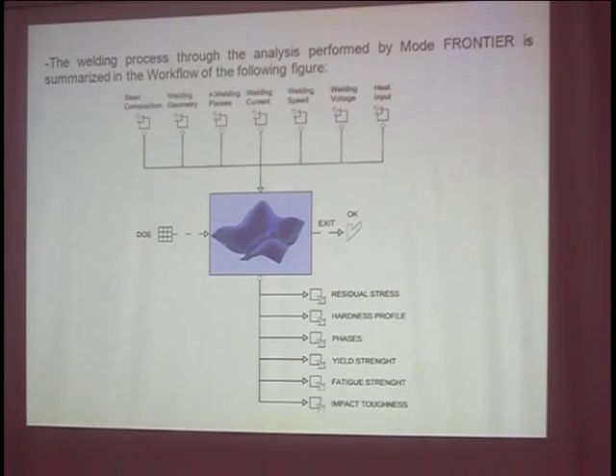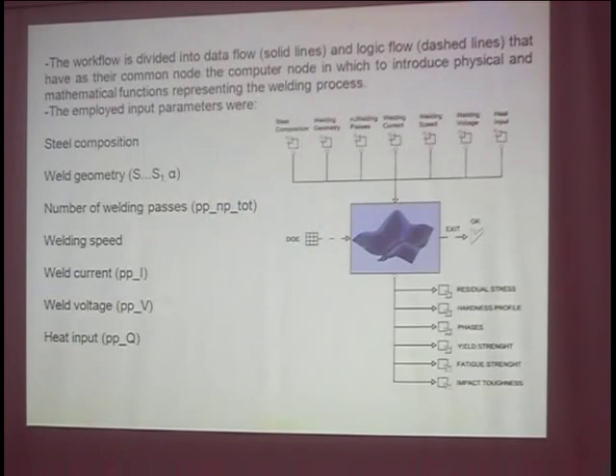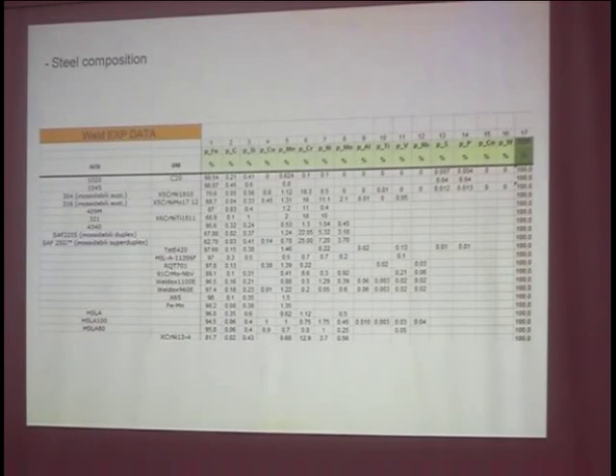The welding process is divided into a lot of input parameters in terms of weld geometry, the thickness of the weld, the angle, the number of passes, which strongly influences the final properties of the welds, the welding speed, the welding current, the voltage, and heat input. Here you can find an example of the different steels we analyzed in this study, in which